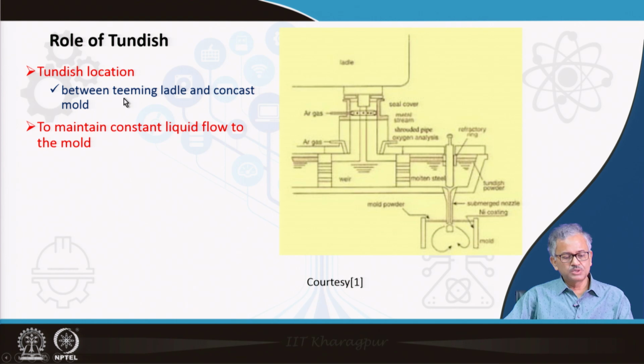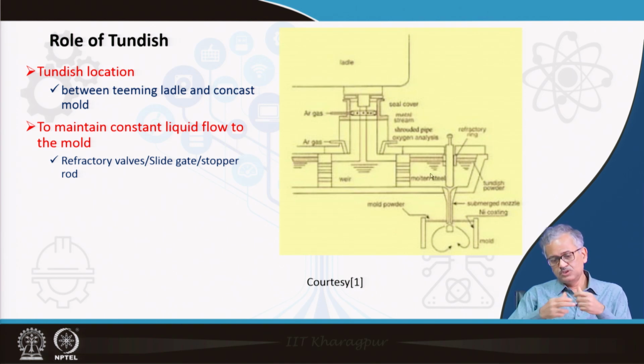Now, that is the tundish location we have talked about, and the function is to maintain a constant liquid flow to the mold, that you know. For controlling the flow rate, besides the liquid height, because there may be a slight change in the liquid height, especially during the changeover of the teeming ladle, you can control the liquid steel by refractory valves, a slide gate or a stopper rod like this. This is called the stopper rod. You can stop the flow when you do not want it, or you can open the nozzle exit as you want, to control the flow rate if there is some problem with the flow rate control. As such, during teeming, when you pour the liquid steel from the teeming ladle into the tundish, you basically maintain a constant height in the tundish, because the liquid steel empties into the mold at the same flow rate at which you pour it. If there is a mismatch, then you can control it by the stopper rod.